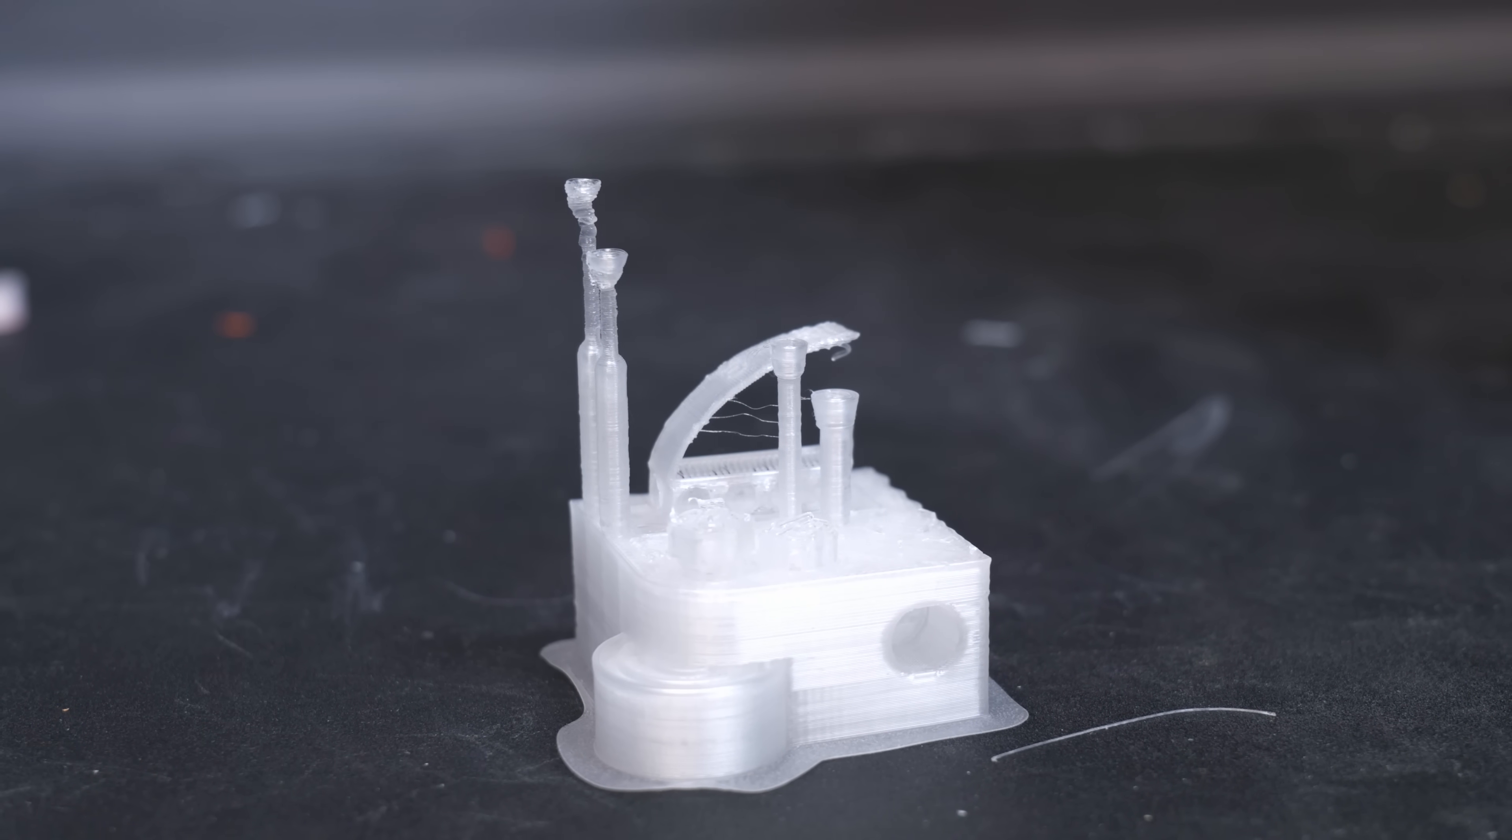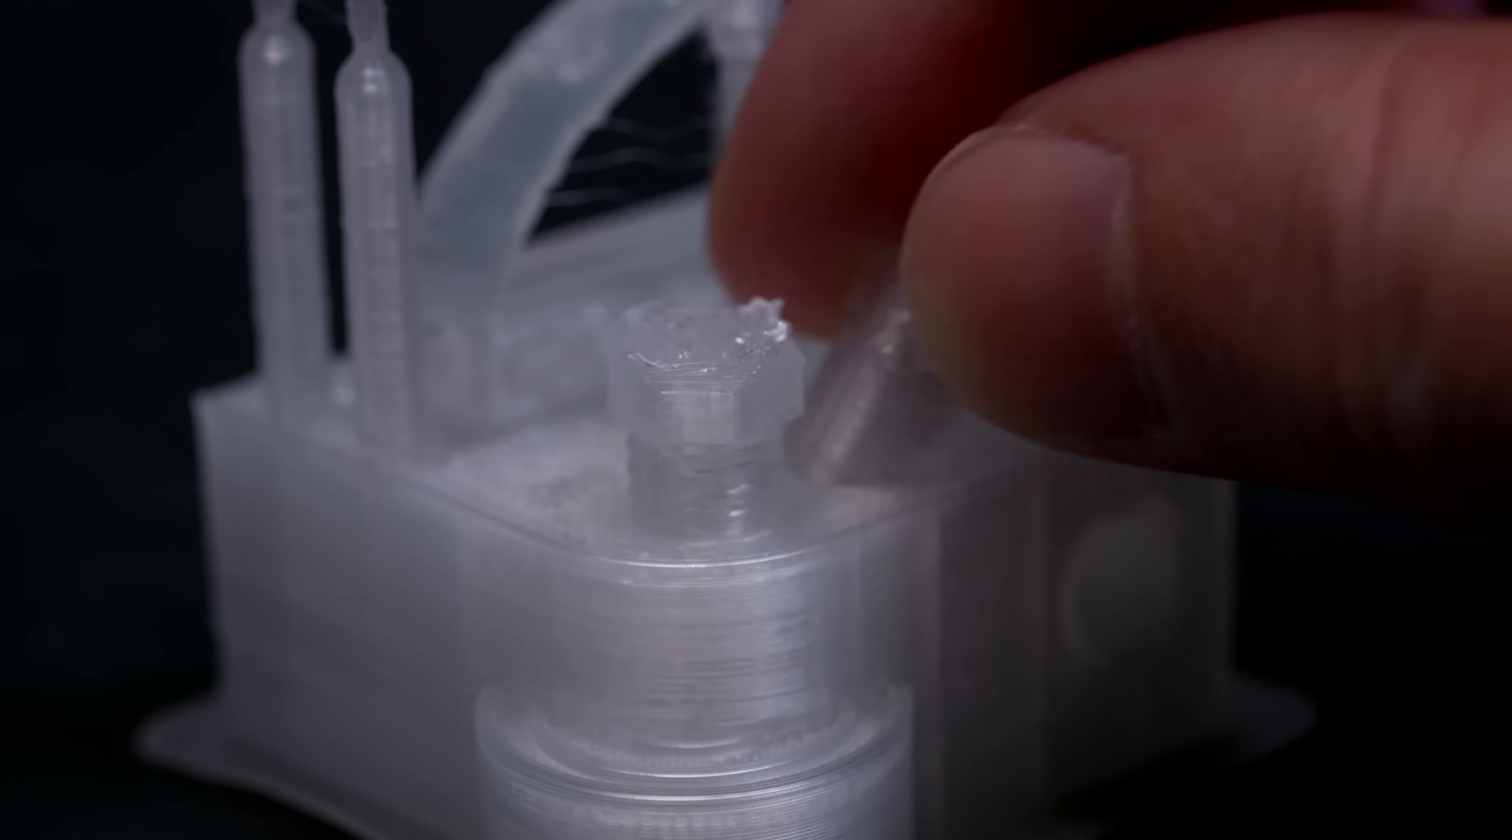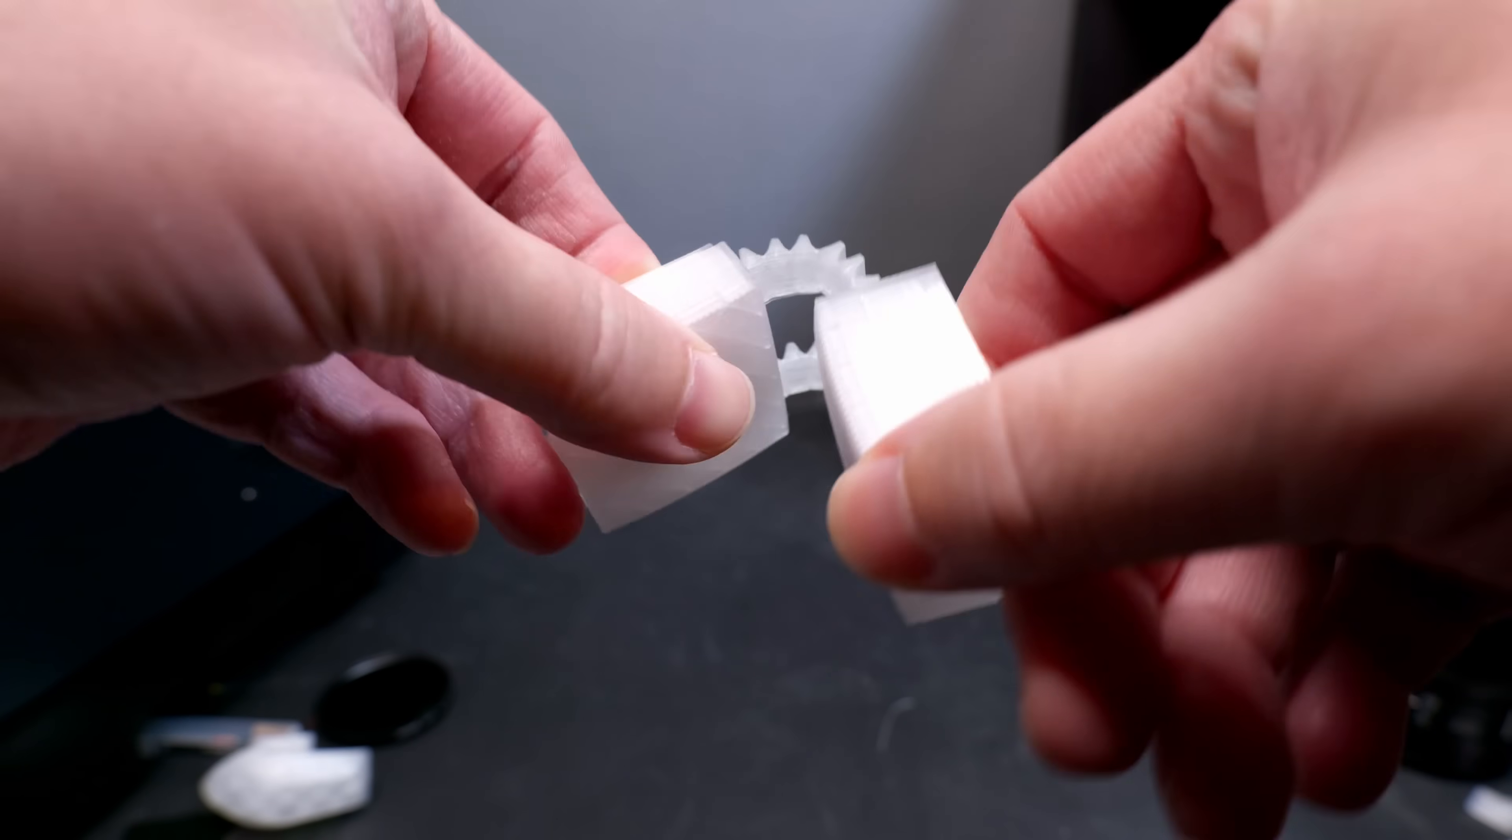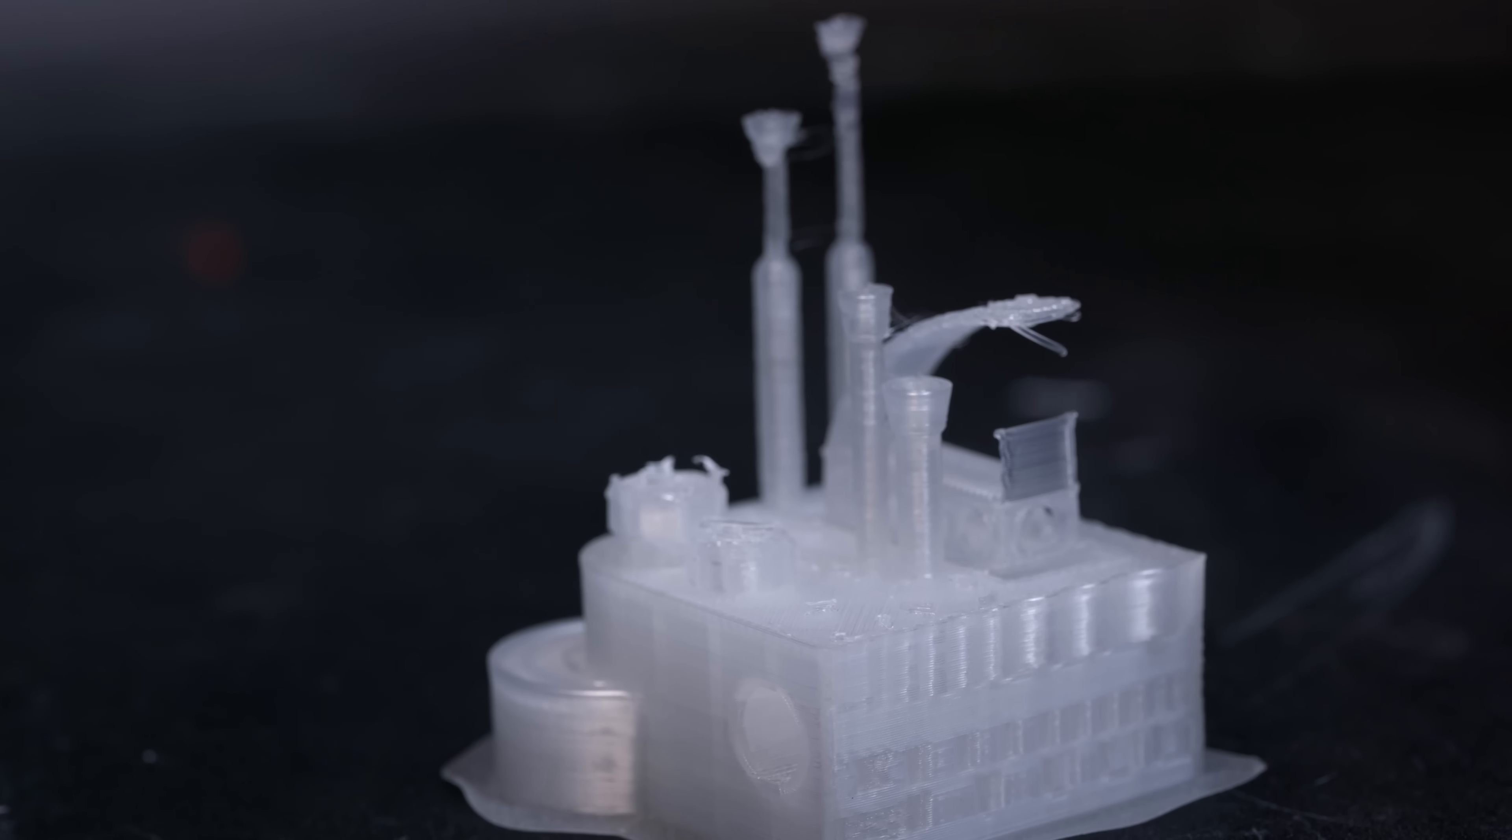The second point is overhangs are actually fine in most cases. The third point is the cube comes with two sizing test parts, a screw and a little peg, and you can see shrinkage in action here. The screw works fine and the cylinder part definitely has some slack in it because, well, shrinkage. Fourth, and this is the only thing I've seen so far that you might really want to consider when designing for polypropylene, thin walls do seem to cause problems sometimes. I don't think it's cooling. I want to say there's some kind of viscosity interaction here, it's pulling into itself. Maybe it's something to do with the contraction we talked about when you're shrinking. It's really strange and it's kind of unpredictable. It happened on this box catch and it happened every time I printed this model except when I printed only half the model when it didn't happen at all. So I think somehow you have to design to try and avoid these kind of situations, whatever they exactly are. I think probably avoiding any kind of thin parts, especially if they are tall.